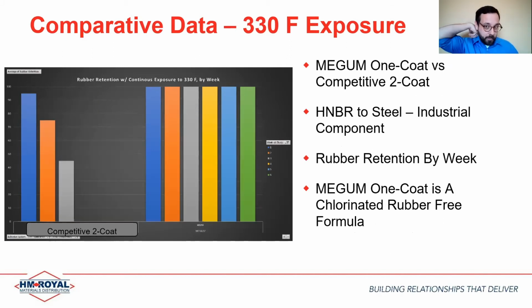In this next example, we put a high-performing OneCoat system up against the same competitive primer. In this case, we're looking at HNBR to steel, again for an industrial roller, and we're still looking at rubber retention by week. In this example, we see the Megum OneCoat, which is free of chlorinated rubber, performs from week 1 to week 6, no variation in performance, 100% rubber tearing bond, while the competitive primer falls apart at the metal almost immediately.